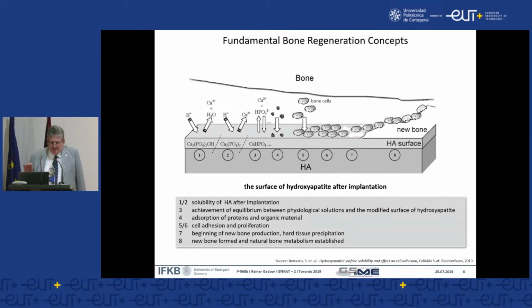I will come back to that later, but in this early phase I want to give you one piece of information. This model is working very well and is correct for solid bulk material. But in the human body and in the typical geometric structures we are dealing with, we have to deal with porous materials. That means the interaction does not only take place at the outer surface, but we have access to the inner surface, so that the pore design, engineered porosity, is crucial to have the best fit. And that is what I want to show you in a minute.